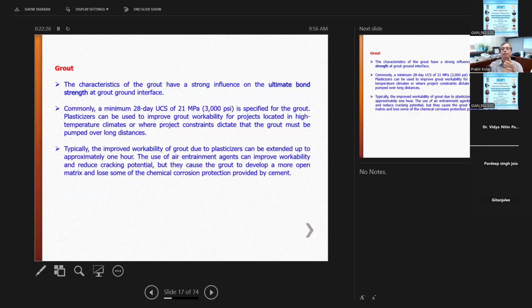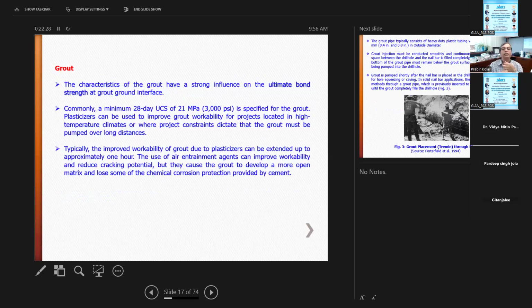So then, ultimate bond strength. The characteristics of grout have a strong influence on the ultimate bond strength of the grout interface. We just check the strength after 28 days. It should be 21 megapascal or 3000 psi. Typically, improved workability of the grout due to plasticizer can be extended for 1 hour.